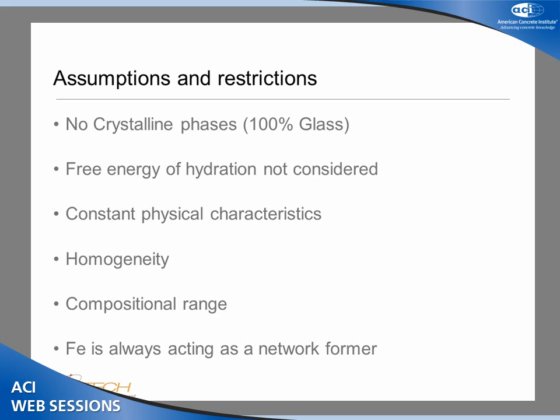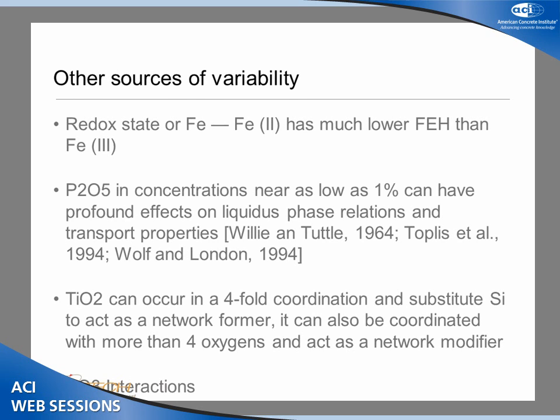The chemical composition of each fly ash particle will vary from particle to particle, basically, and what we see on the chemical analysis of the fly ash is basically just an average of all the chemical compositions of all the particles. We also assume that iron is always acting as a network former, and that's not always the case, depending on the burning conditions. It can be iron 2 or iron 3, so that would change things a little bit. Also, we didn't consider the phosphate concentration. That also can have a big influence on the glass network. Titanium could substitute silicon in a fourfold coordination. We didn't consider that either.